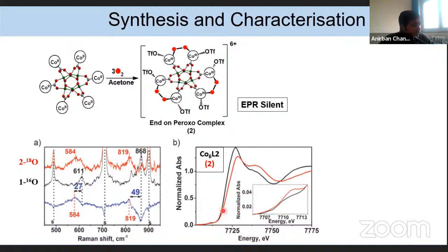From the cobalt K-edge data, we can see that the black one is for the hexanuclear cobalt complex, which is showing a 1.6 electron volt blue shift for the peroxo complex. So the 1.6 electron volt blue shift confirms the oxidation of the cobalt(II) center to cobalt(III) center. And you can see that the pre-edge value also shifted towards higher electron volt for the peroxo complex compared to the starting complex, which also indicates the higher ligand field strength in the peroxo complex compared to the starting cobalt-6 complex.